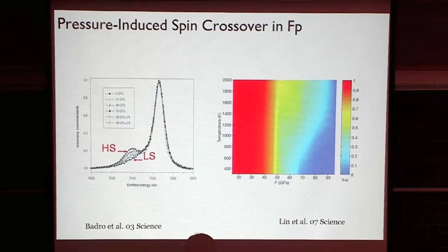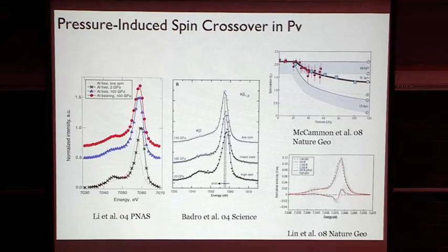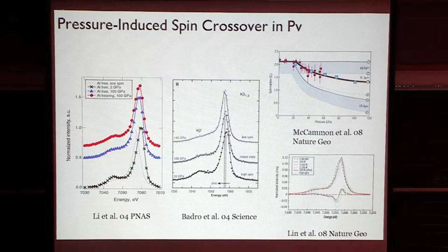At 100 GPa, for different alumina-bearing and alumina-free samples, you have either an intermediate or mixed spin state, because the satellite peak is a lot more subdued. It's much smaller, but it's still there. It's probably half of the height. And then there are other studies saying, oh, actually it goes away by 145 GPa. But this study hasn't been confirmed.